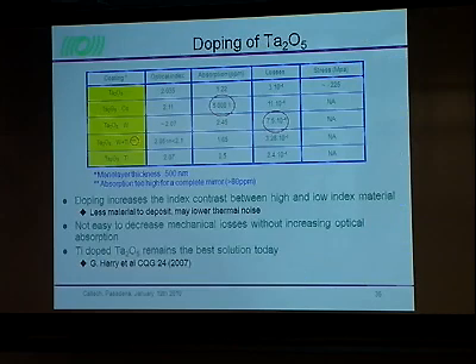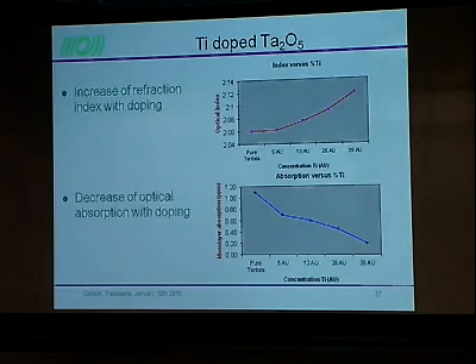The other path consists in trying to improve the tantalum pentoxide by doping the material with other elements. Several tests were done, and the bottom line is that titania doped tantalum remains the best solution. It allows to decrease the losses to the range of 2 10 to the minus 4, and also it allows nicely to decrease the absorption of the coating. This is a very likely situation, because as you dope the tantalum with titania, you not only increase the index of refraction, so you reduce the amount of material you need, but you also decrease the optical absorption.